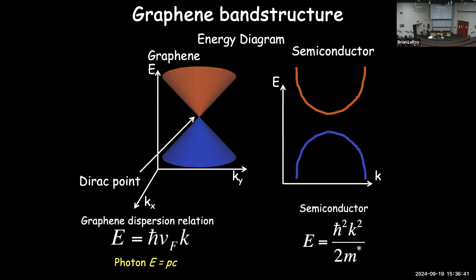And that has this relationship where the energy is linearly proportional to the momentum, with this proportionality just ħv_F. And I want to contrast that with most typical semiconducting type materials, which have an energy versus momentum relation that has energy goes as k squared. So more like a free particle here with some effective mass in the denominator here. Graphene is more like photons, right? Energy is just directly related to momentum.